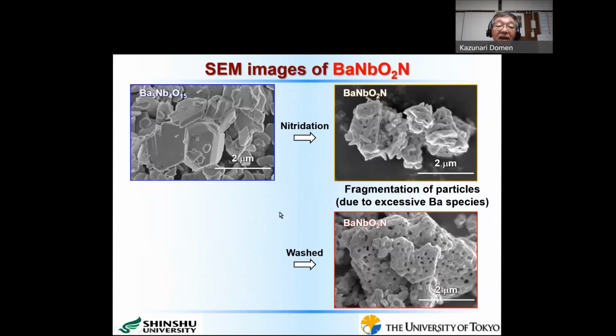And here I show the SEM image of these materials. This is the barium niobium oxide material, the precursor material. Then after nitridation, we obtain this kind of barium niobium oxynitride. But at this stage, this material still contains some impurity phase. So we remove that impurity phase by aqua regia and then wash it out. We obtain this kind of porous barium niobium oxynitride material.